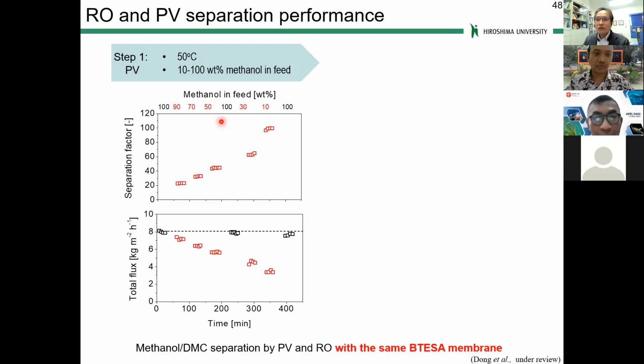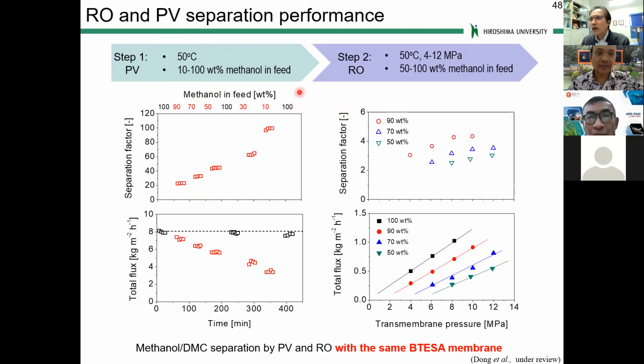Now we move to the comparison of the reverse osmosis and the PV separation performances. First, this membrane was initiated from PV, from 100% methanol, 90, 80, 70, and then 30 to 10, and then back to 100 again, pure methanol. On the right side, followed by the reverse osmosis experiment. Exactly the same membrane was used for methanol DMC separation in pervaporation and reverse osmosis. And then we try to analyze these performances.